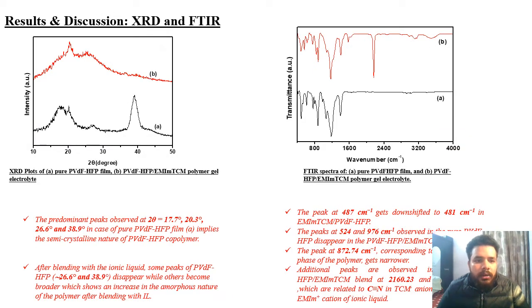First of all, you can see here the XRD graph of pure PVDF-HFP film and PVDF-HFP and EMIM-TCM blended film. The black portion is showing the pure PVDF-HFP film XRD graph, and the red portion is showing the ionic liquid doped PVDF-HFP polymer film graph. Pure PVDF-HFP shows 4 peaks at 17.7 degree, 20.3 degree, 26.6 degree, and 38.9 degree. These peaks show the semi-crystalline nature of PVDF-HFP copolymer.